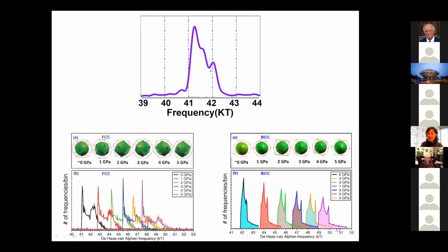Now, if you look at this lithium peak compared to what we theoretically calculate for the FCC versus BCC, it looks like two sets of peaks exist, one going back to BCC and one going to FCC. So that is the first measurement where we could really resolve these peaks, and we are very excited about it. This is unpublished work that we're working on now.